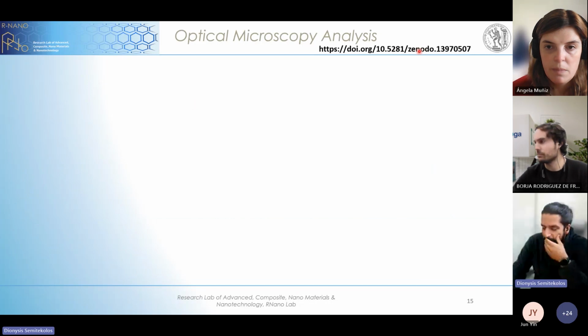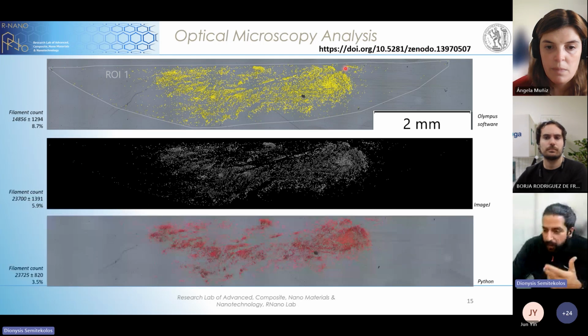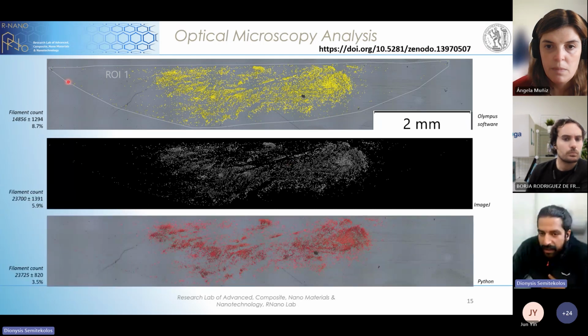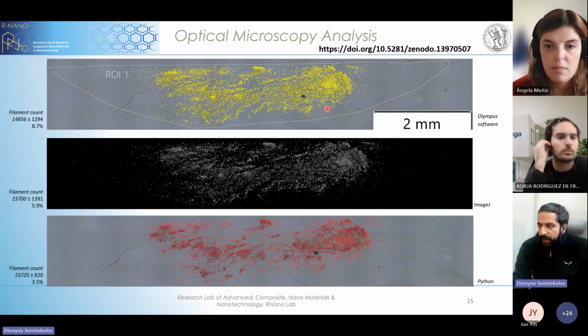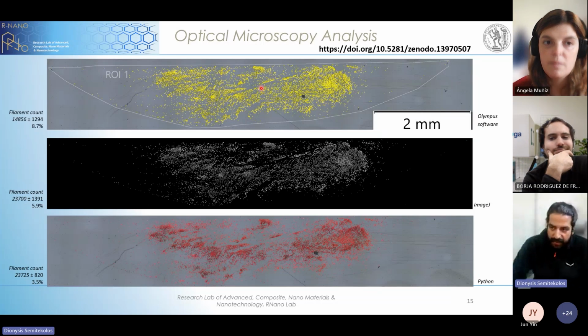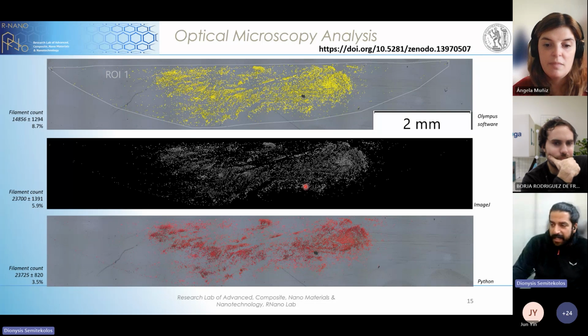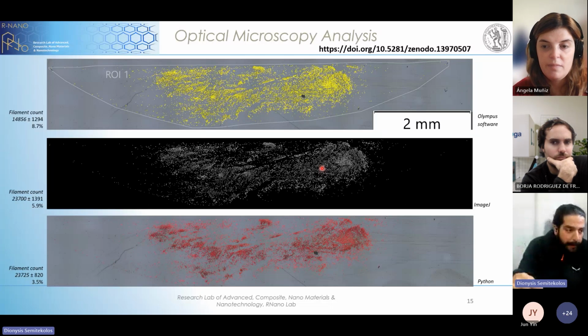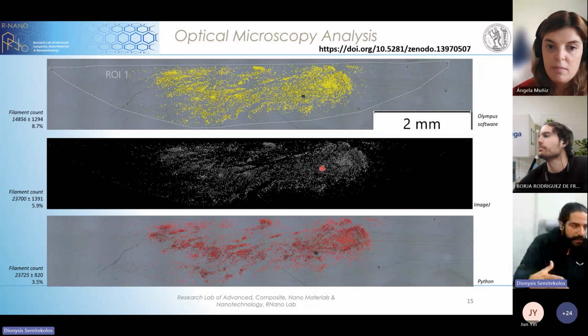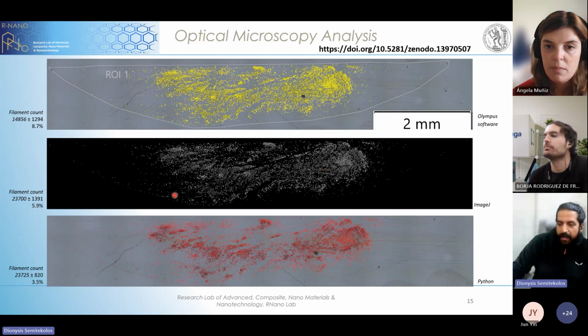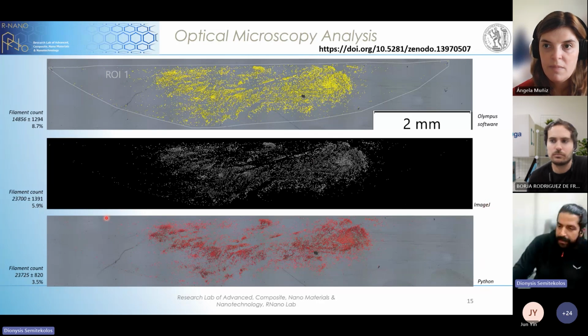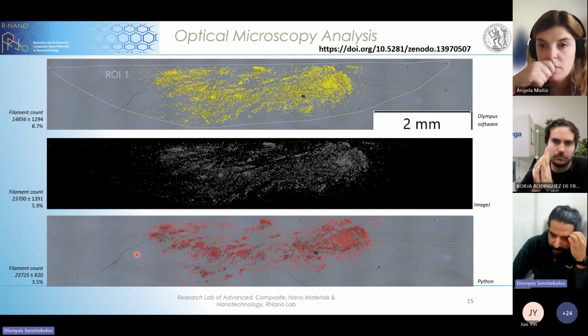So you can visit this site here to check our scripts that we developed in Python. And as you see, we tried 3 different approaches: the Olympus software, the Microsoft software, ImageJ, and Python. The Olympus software failed miserably, unfortunately, due to the fact that it cannot track adjacent fibers. ImageJ was a very decent approach. However, it is manual, so you need to handle the software manually to get results for a single image. But when we mimicked the ImageJ approach in Python and wrote our own script, we were able to copy the algorithms that ImageJ uses, and in 1 or 2 minutes have all the results that we needed on our monitors.